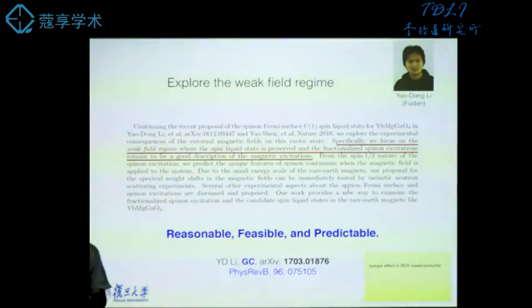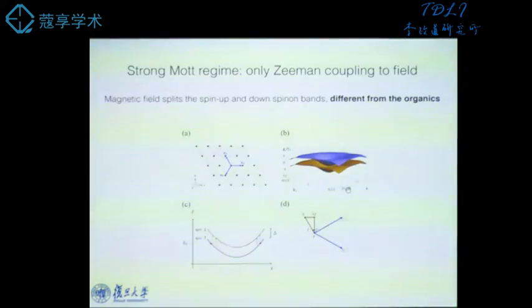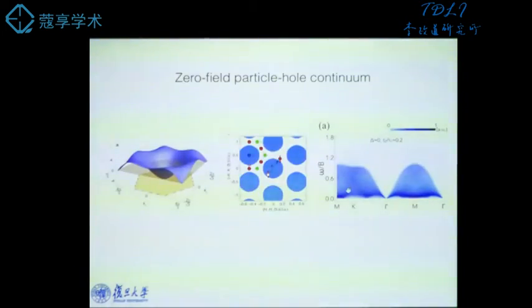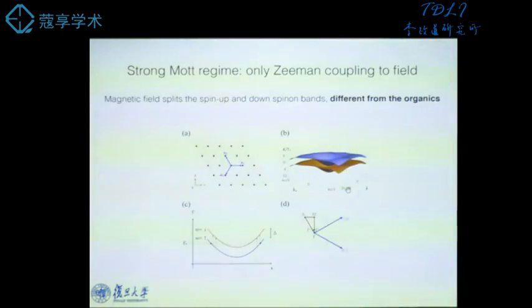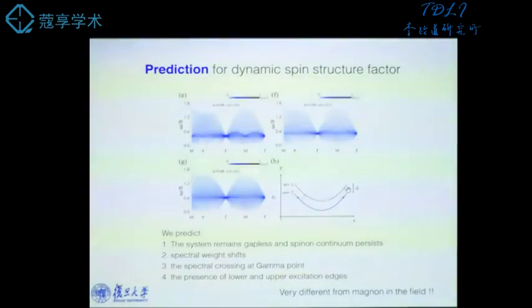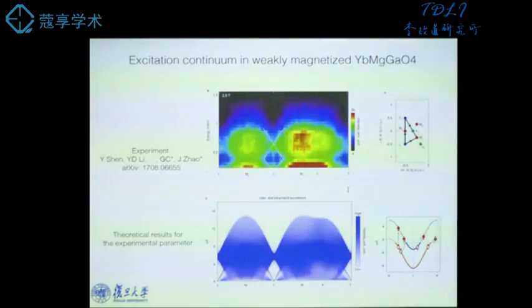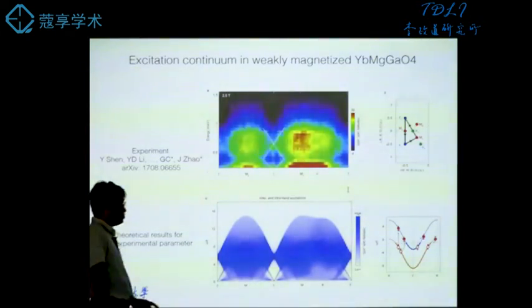Then you can make a prediction. The spinon remains to be the description of the magnetic state. So this is a prediction we made with my student. Originally the spinon bands are degenerate, up and down degenerate. Now you apply Zeeman coupling. So you get a relative shift between these spin-up and spin-down bands. So then the excitation can be predicted. So this is a theoretical prediction.